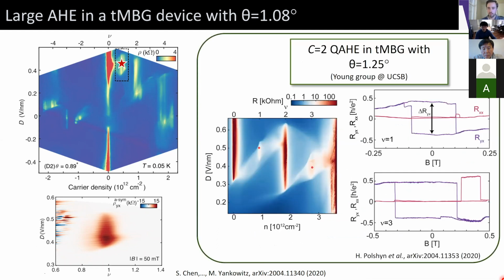Okay, and I should note that this was also done in Andrea Young's group in samples with different twist angles, about 1.25 degrees. And there they saw quantum anomalous Hall at both 1/4 and 3/4 filling, both with near quantization with Chern number of 2. Whereas our results weakly suggest that at this twist angle of 0.9 degrees, the Chern number is 1. So there's more that needs to be done, but this motivates that, in fact, we not only can realize intrinsic quantum anomalous Hall in these samples without external alignment to other crystals, but also the Chern number might be tunable with twist angle or perhaps even pressure.